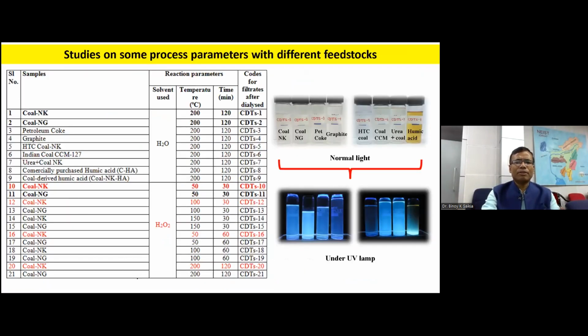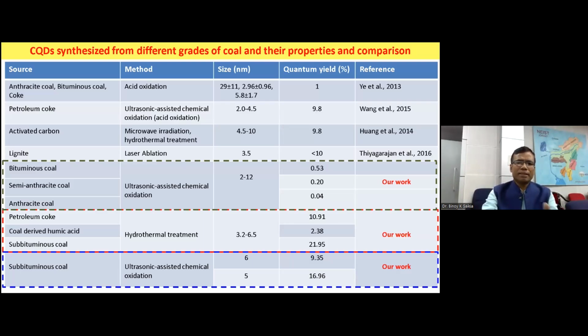And we also optimized with different types of raw material. This is a table. I will not go into details, but you can see that we have done a lot of samples, precursors at different temperatures and different times, and we found that it optimized. In the next slide, with reference to some of the latest and prominent literature, we compared and found that this coal-based quantum dot, or quantum dot, has a much higher yield than other raw materials and other drastic methods. You can see the acid oxidation done by Ye et al., and the ultrasonic-assisted and the microwave. Microwave is a very drastic treatment, and laser ablation is highly costly. So we found a very simple oxidation method, although we have used ultrasonic, but chemical oxidation without inorganic acid.